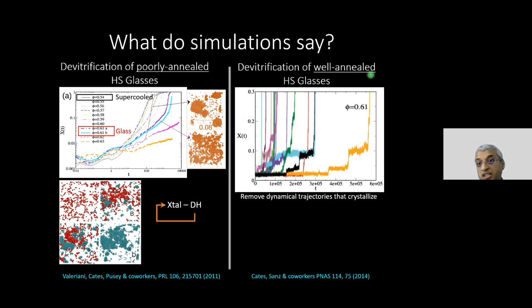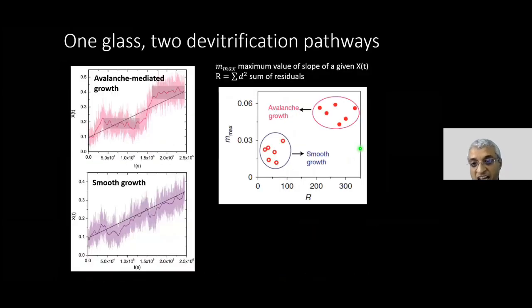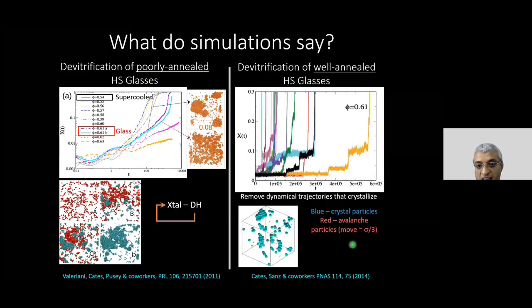And what they see, this is once again for phi equal to 0.61, which is precisely what they did earlier for a poorly annealed glass. But now, if you were to plot x of t as a function of time, you essentially see these nice steps, just like the one that we saw. And this is once again a movie. I'm not going to play it here, but this essentially says the same thing.